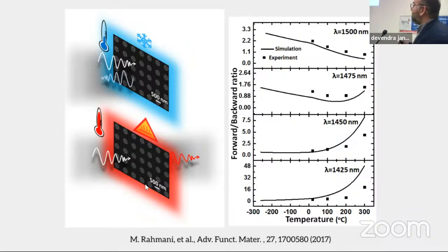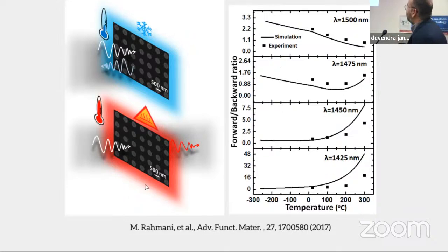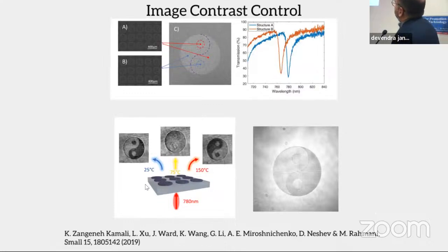So I want to remind you that at these wavelengths, silicon doesn't absorb light, so it is either reflection or transmission. But here, as you see, the biggest problem was the high temperature. So what we did, we designed some better nanostructures with better physics. As you see here, these nanostructures, I don't know whether you can see them clearly. There are some holes inside them. So these holes actually break the symmetry and let us generate these sharp resonances.